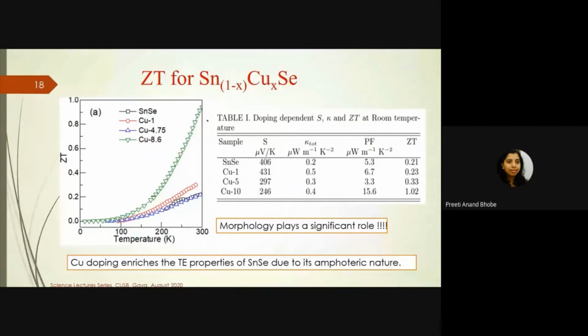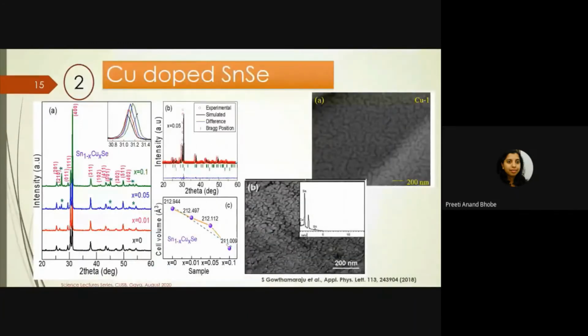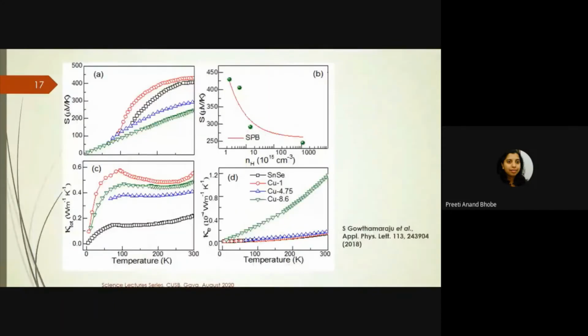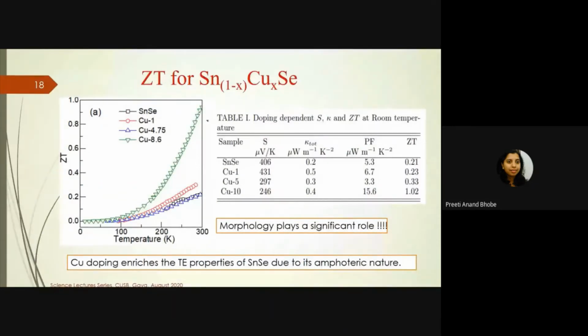But that should not bother you too much, because in all this thermoelectric material research, what is important is how good the ZT of the material is. So if, compared to your pure SnSe, by putting in copper my ZT has improved, then it has improved. I only have to tell what the reasons for its improvement are. Here, we realize that it is not any of the factors affecting thermal conductivity or electrical conductivity. It's basically the morphology. If you remember in my first slides, I said that the morphology changes a lot. Because of this, the scattering of phonons changes a lot from one grain to another, and that is what gives rise to very low thermal conductivity and hence a good ZT for my materials.